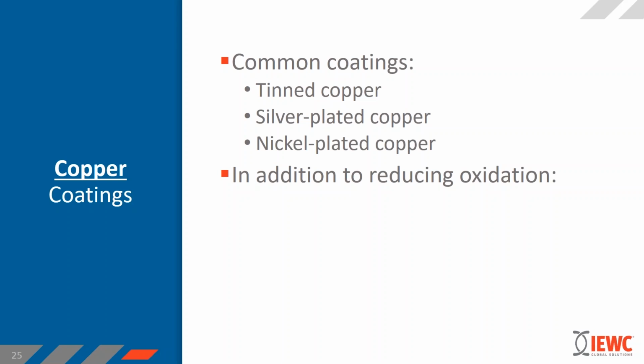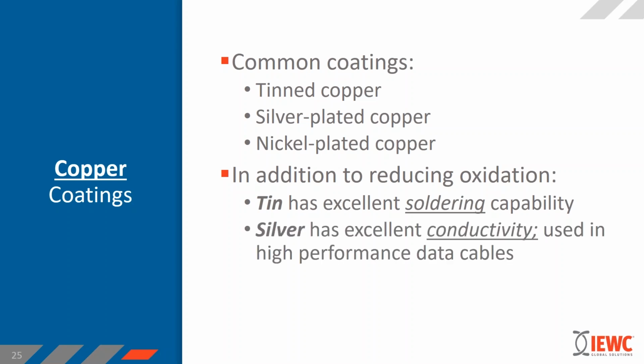But in addition to reducing oxidation, tin plating also has another advantage, and that is that tin has excellent soldering capability. So if your application needs you to solder that conductor, say to a printed circuit board or to anything else, the engineer will often call out a tin-plated conductor. In this case, it's not about heat, it's about getting that perfect electrical connection. And tin-plated copper is better than bare copper. Or, if you remember, I said that silver has slightly better conductivity. In some high-performance data cables where you've got to transmit a lot of data at very high speed down a conductor, you're going to use silver-plated copper. So it's not just about heat, it's also about transmission, how we need the best conductivity available.